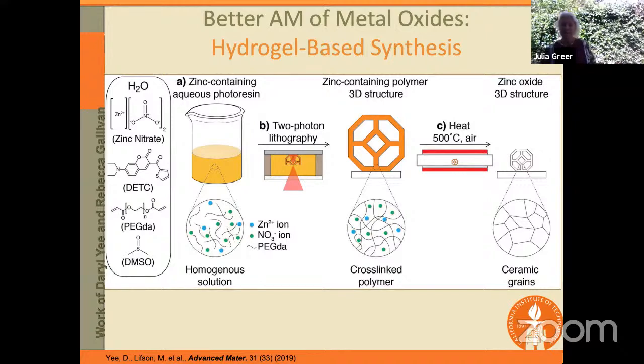So we have been exploring other ways of creating the same or maybe different kinds of metal oxides. And what my students came up with is the hydrogel-based synthesis. So you take a hydrogel, and of course, this is all aqueous environment, so it's all just effectively water. And what you can do is leach in and swell in various metal salts. In this case, it's zinc NO3 into this polyethylene glycol hydrogel.